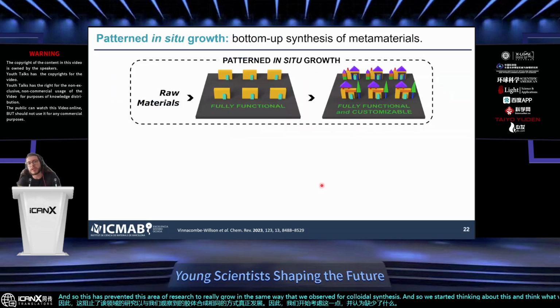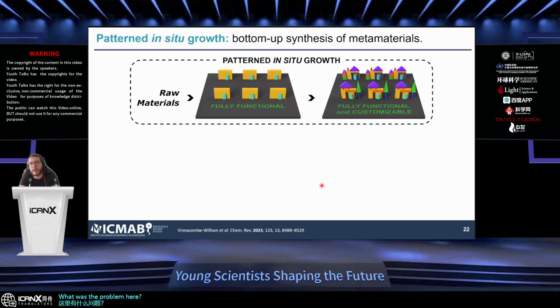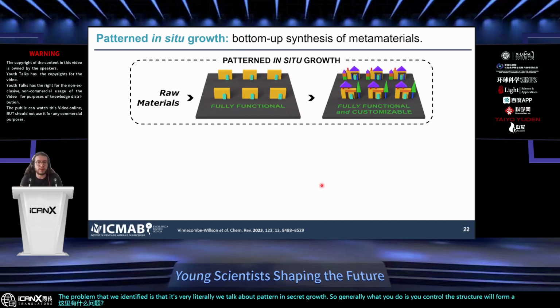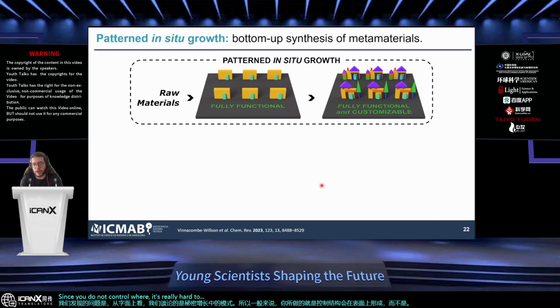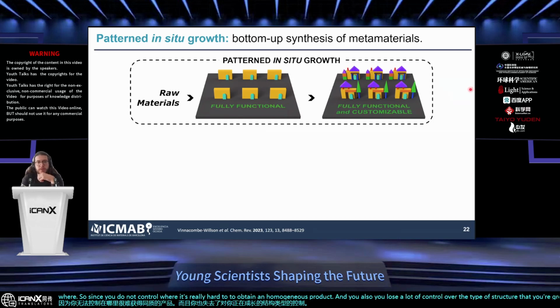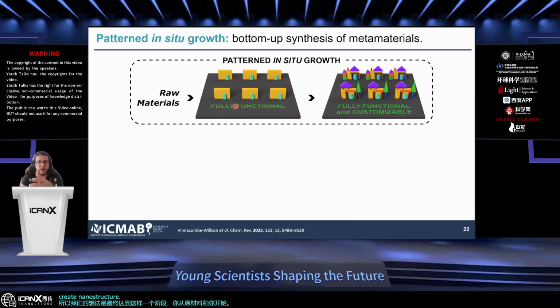The problem that we identified is that we literally talk about patterned in situ growth. Generally, what you control is that your nanostructure will form on the surface, but not where. And since you do not control where, it's really hard to obtain a homogeneous product, and you lose a lot of control over the type of structure that you're growing. And so the idea is to finally reach this kind of stage where you start from raw materials and you create nanostructures that are fully functional and also customizable. So I can think about a multi-step growth, the same way that we do in colloidal synthesis, but directly on the surface at specific locations.